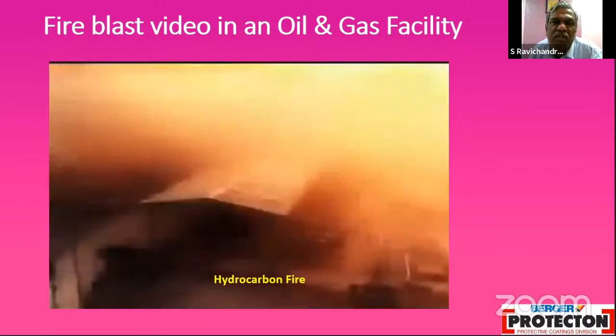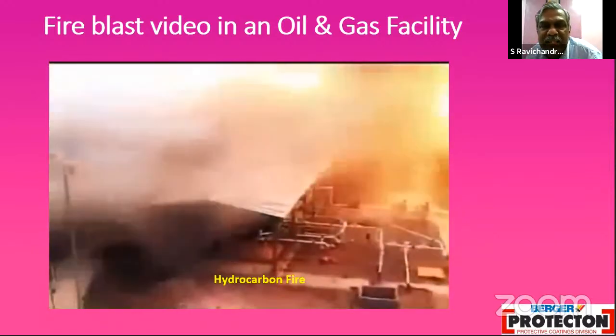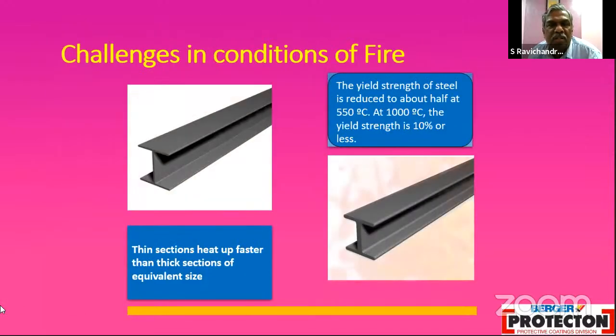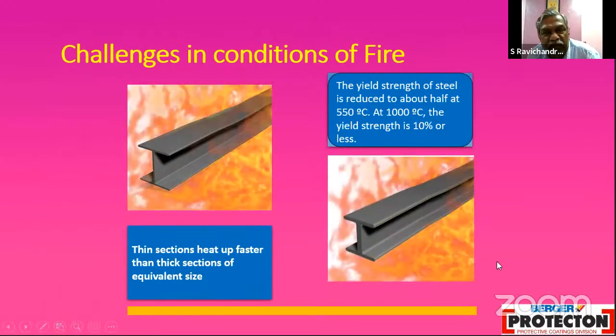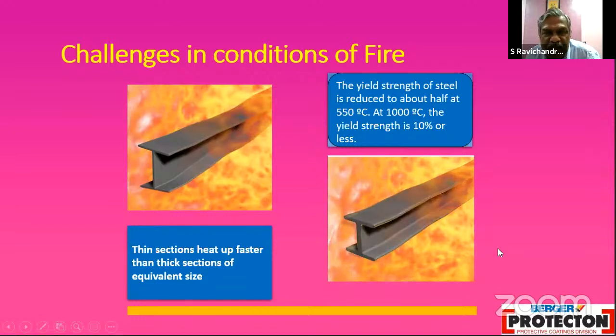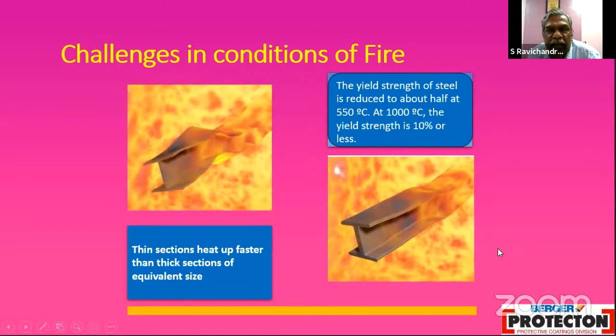This temperature is more than 1200 degrees. Any steel will melt. So this is how it is. Steel, when subject to temperature, crossing 550 degrees, loses its strength to hold. And this is where paints come in, to ensure that the steel or the concrete can be protected for a period of 30 minutes, 60 minutes, or even 120, 180, 240 minutes. For that length of time, we can ensure that the steel can be protected without the effect of fire reaching it. And that is total insulation to the steel or the concrete.